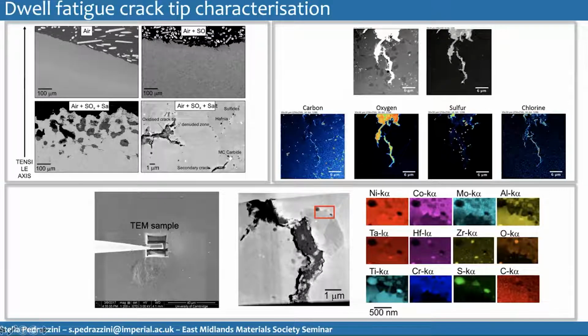So in this case, I was able to show that these particles at the grain boundaries are titanium and chromium rich, and they're sulfides. Yes, sulfur overlaps with molybdenum even here, but between the SIMS and the TEM, this is very convincing evidence that those are sulfides. And the hafnium and tantalum formed oxides with a bit of zirconium in them as well. These are the bright particles that we observe here, whereas sulfides are the dark ones. So now I got a bigger picture of everything that's going on.